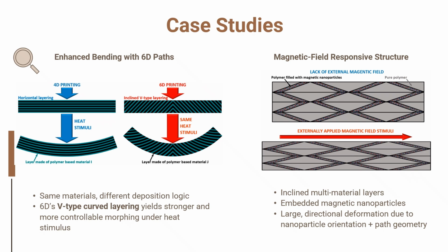To illustrate the impact of 6D printing, let me show you two representative case studies. On the left, we compare classic 4D printing with our 6D approach under identical heat stimulation. Both examples are made of the same materials, but their deposition logic is different. In 4D printing, the layers are horizontal, which limits the bending intensity and controllability. In contrast, 6D printing uses inclined V-type curved layering. The orientation allows the structure to bend more strongly and more predictably when heated. So simply by changing the deposition geometry without changing the material, we achieve significantly enhanced morphing performance.